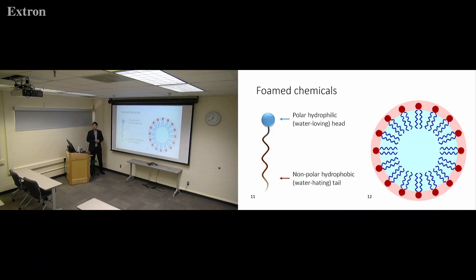Then, the other method is foam concrete. This relies on the use of foaming chemicals. These are surfactant molecules that consist of one polar head and one non-polar tail. So this head is water-loving and the tail is water-hating. When you mix or stir it, bubbles self-assemble and give volume and stability to